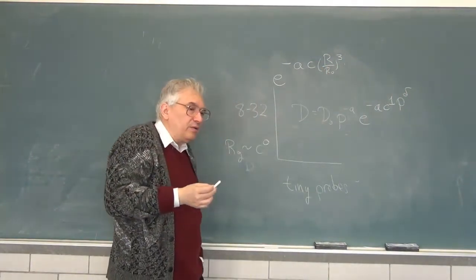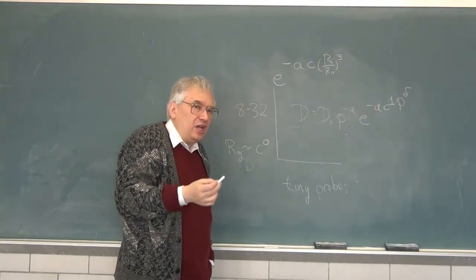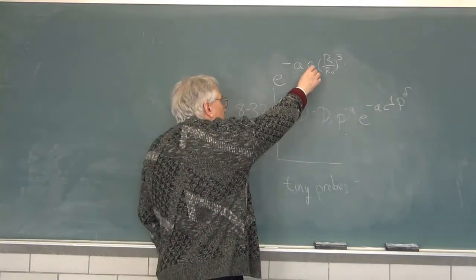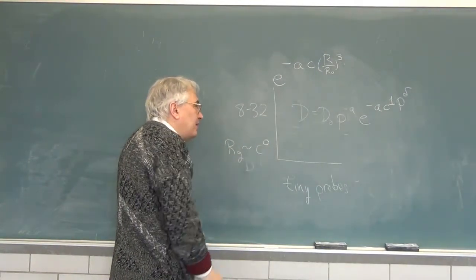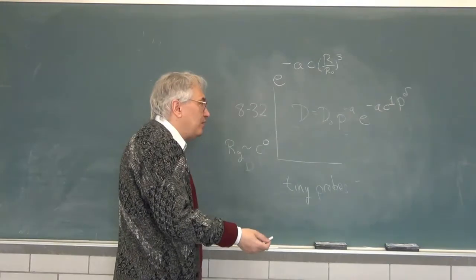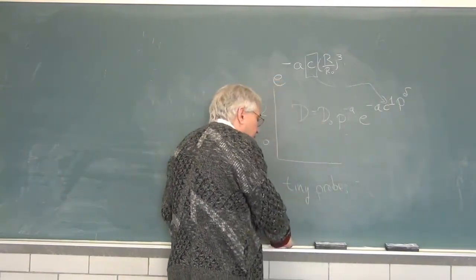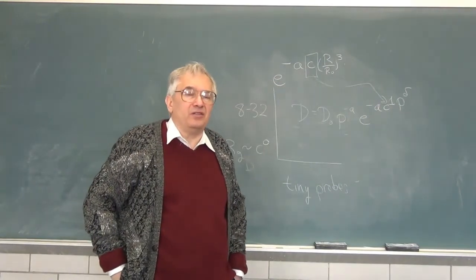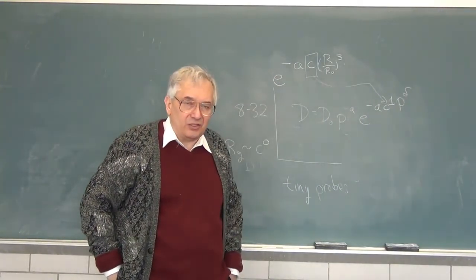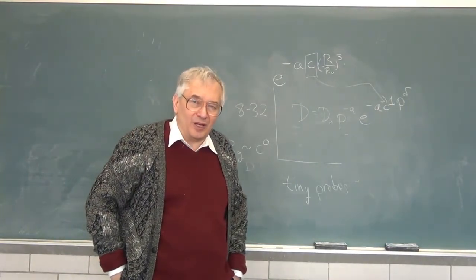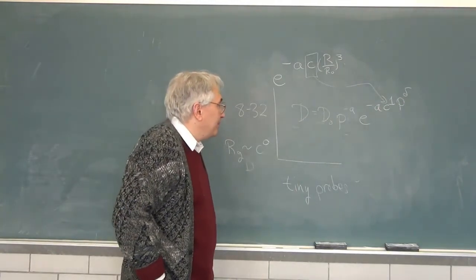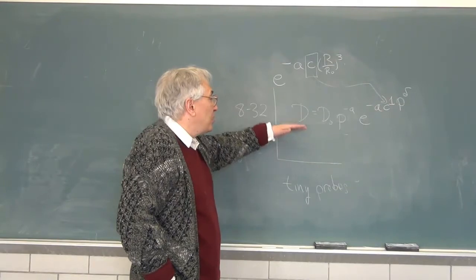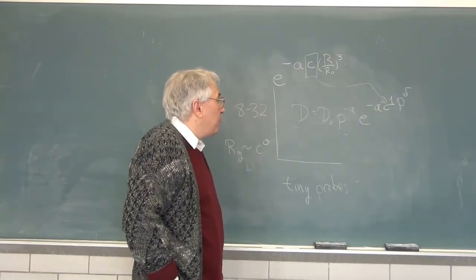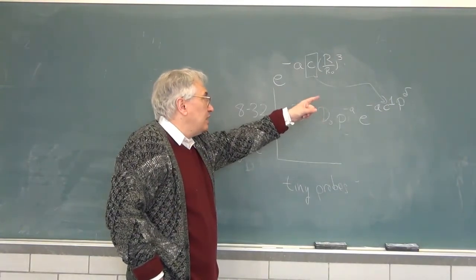And what we had from dielectric relaxation, this unity between chain size contraction and stretched exponential rather than simple exponential behavior. Here we have chains that do not contract. Their radius is independent of concentration, and therefore there should be all of the concentration dependence. And that is exactly what you find. The concentration dependences you see in the figure are all pure exponentials in concentration. And because they are pure exponentials in concentration, it's e to the minus a, c to the first. That's a coherent description of what's going on, and it's coherent in terms of the stretched exponentiality arising from chain contraction.